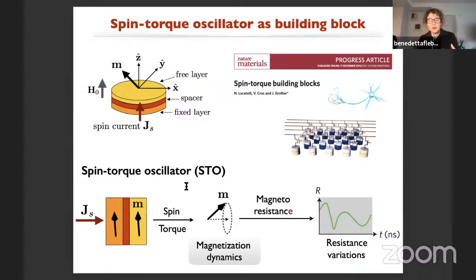When we started learning about non-Hermitian systems, we decided to look at a spin torque building block as really a starting point for realizing a similar non-Hermitian topological phase in a magnetic system. So a spin torque oscillator is nothing but a tri-layer composed of a fixed layer, a spacer, and a free layer. For our purposes, the only thing that we need to know about this system is that a current will pass through a fixed layer, fixed because the magnetization direction is fixed. It will get spin polarized, then go through the spacer and exert a spin torque on this magnetization, this magnetic order parameter. So what we are really interested in is only the dynamics of this magnetic order parameter and the fact that we can tune it by spin current injection.